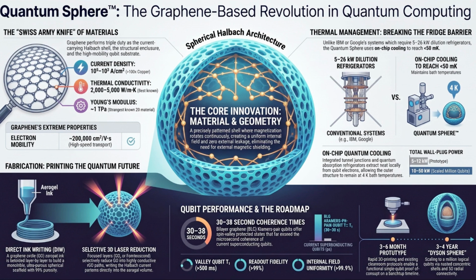the substrate. Yes, absolutely. Think about how a traditional planar chip is manufactured. You start with a flat silicon or sapphire wafer. Then you deposit layers of aluminum or niobium to create the superconducting circuit. Right. Then you might use other materials for insulating layers. These are completely different materials with entirely different atomic structures. Okay. When you take that multi-material sandwich and freeze it down to near absolute zero in a dilution refrigerator, those different materials contract at different rates. Oh, I see. This creates thermal mismatch. The physical stress literally tears at the microscopic interfaces between the metals and the silicon.